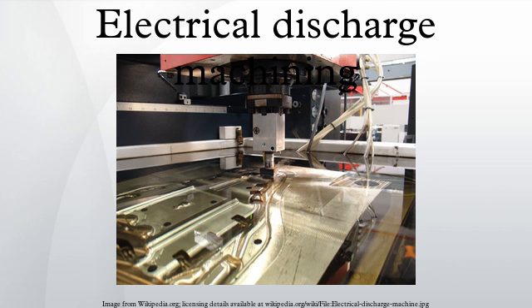Among these, the model from Singh and Ghosh reconnects the removal of material from the electrode to the presence of an electrical force on the surface of the electrode that could mechanically remove material and create the craters. This would be possible because the material on the surface has altered mechanical properties due to an increased temperature caused by the passage of electric current. The authors' simulations showed how they might explain EDM better than a thermal model, especially for small discharge energies, which are typically used in micro EDM and in finishing operations.